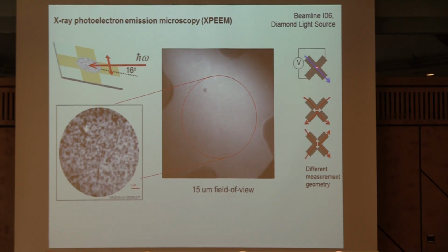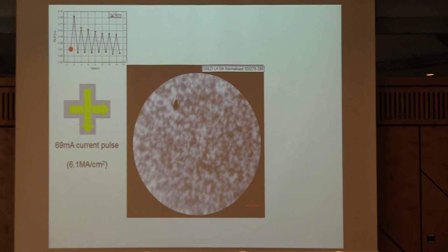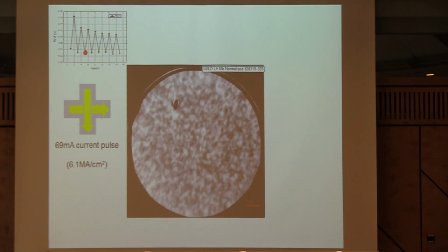So this is the measurement of the transverse AMR. And what I'm going to show you now is a sequence of 16 switches that we've seen in the transport before, but this is now simultaneous transport and beam imaging. So we're going to start here, and the black and white contrast is really ultimately the vertical and horizontal alignment of the strings. You have to watch quite carefully. Up here in the corner is the switching from the electrical signal measured in parallel. And what we're looking for is a light, dark pattern.